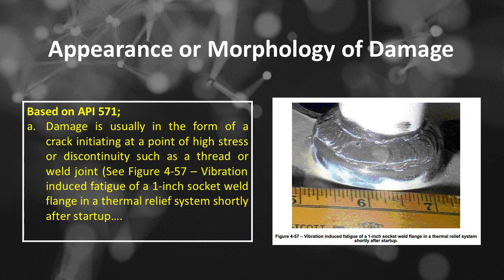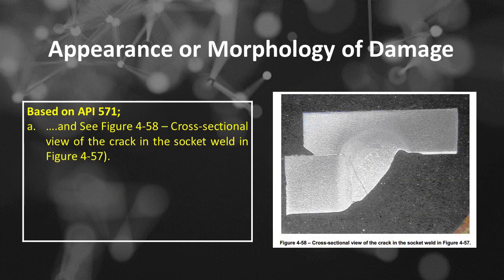Appearance or morphology of vibration-induced fatigue damage mechanisms based on API 571. The first is damage is usually in the form of a crack initiating at a point of high stress or discontinuity such as a thread or weld joint. See Figure 4.57, vibration-induced fatigue of a 1-inch socket weld flange in a thermal relief system shortly after startup. And see Figure 4.58, cross-sectional view of the crack in the socket weld in Figure 4.57.